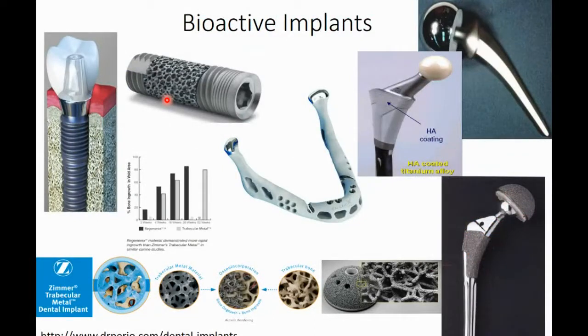As you see here, there is a dental root which was launched by Zimmer in 2014. In this dental root, there is a strategic location where there is an open porous structure. This is a trabecular metal, and here tissue can grow into these pores. Therefore, you have better interfacial bonding. Similarly,